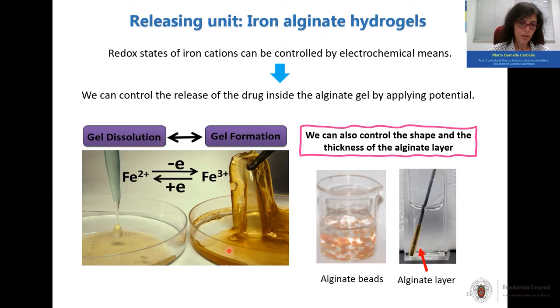If you take a look at the picture on the screen, if we prepare a solution of alginate in the presence of iron plus 3, the solution immediately becomes a gel, it becomes gelified. But if we reduce this iron plus 3 into iron plus 2, the gel gets dissolved with the subsequent release of the drug that we had entrapped in it in a very easy way, just by applying a potential. It is also important to note here that we can control the shape and the thickness of the alginate layer.